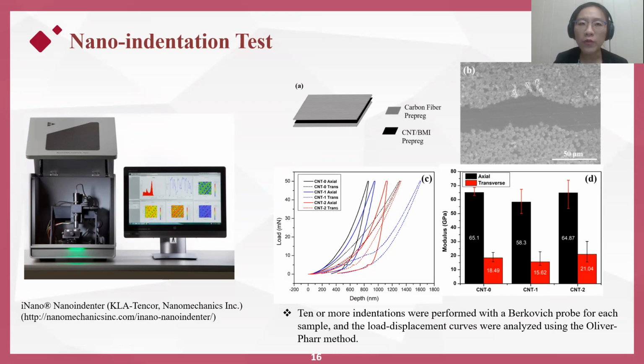It is very obvious that the reduced modulus shown increased significantly, probably 2 to 3 times, compared to the tensile Young's modulus that we talked about earlier. This is probably because the 2 measurements are very different in nature. The higher modulus from nano-indentation could originate from the characteristics of the CNT composites, in that the tensile properties